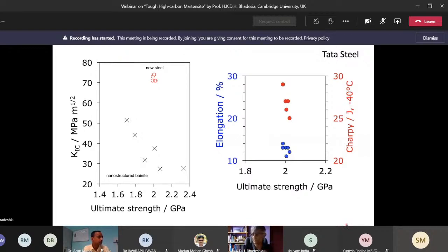Okay, so the basic principle that I explained earlier is that if you make your martensite plates extremely fine, then you will get strong martensite and tough martensite without tempering. And the second criterion is that by making the martensite form from severely deformed austenite, we are presenting any crack with many different crystallographic orientations, and that will make cleavage crack propagation more difficult.